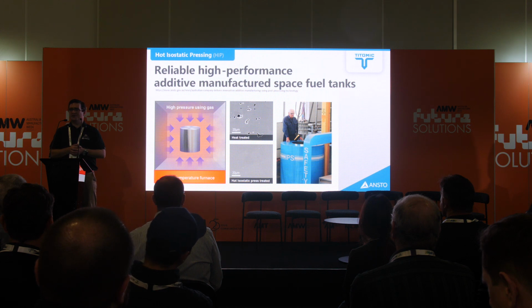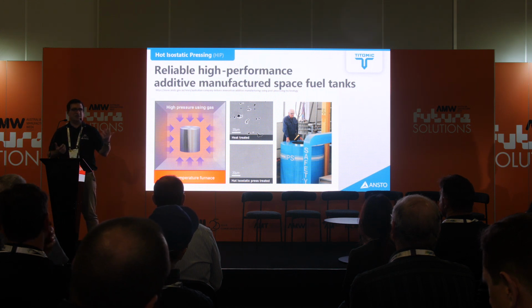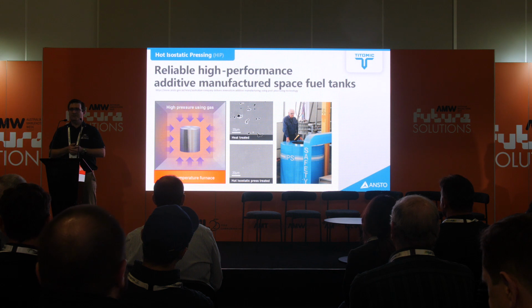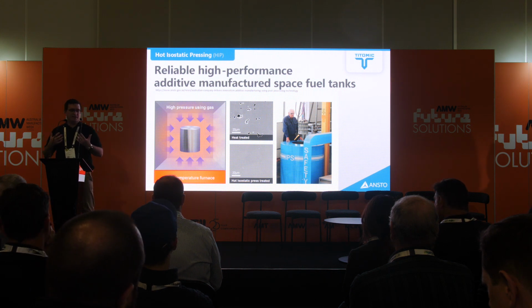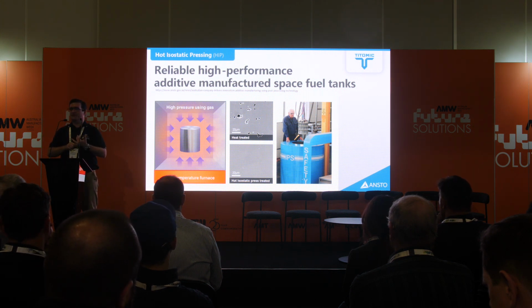But what happens when you've got defects in the structures that you just can't resolve by changing your build parameters? ANSTO has a long experience in a process called hot isostatic pressing. This is where you take a high temperature furnace with a high pressure of gas that's pushing on a part equally on all sides to do a heat treatment. So what's happening here is you can refine the microstructure and reduce voids and cracks in a part by applying this pressure equally across all the part at critical temperatures.